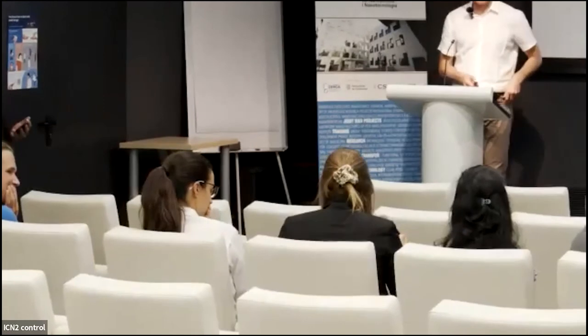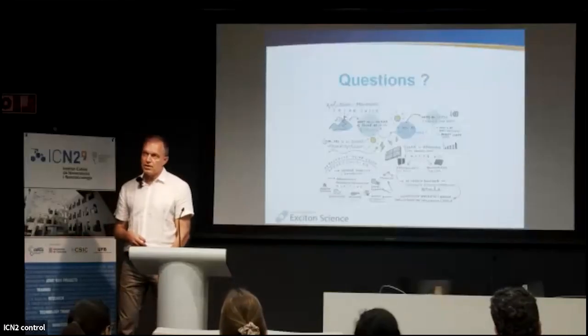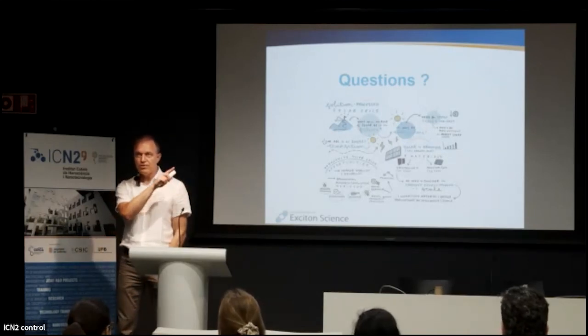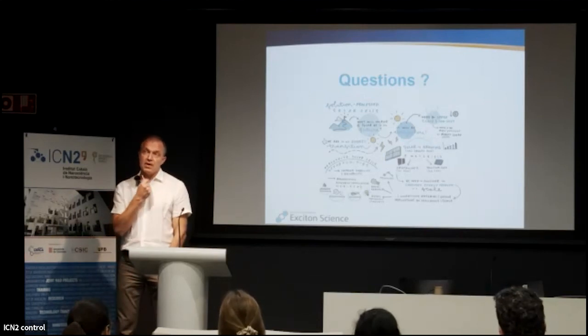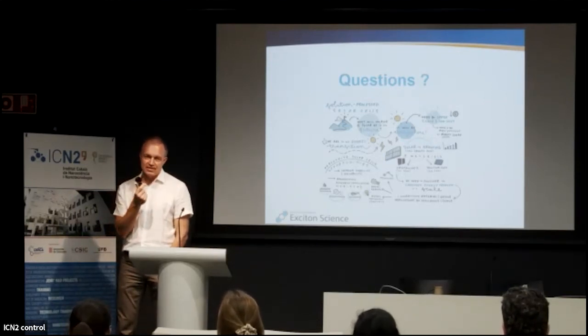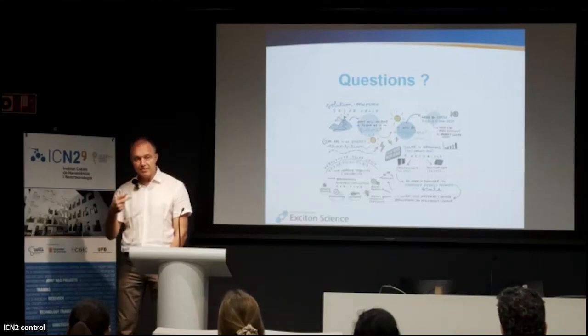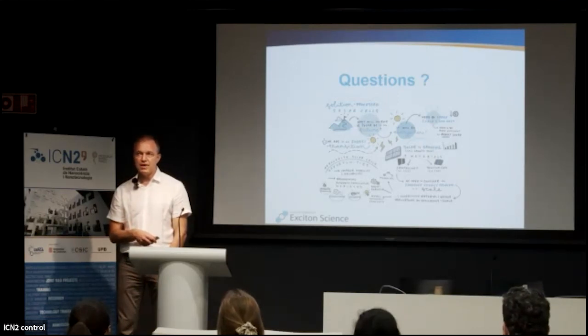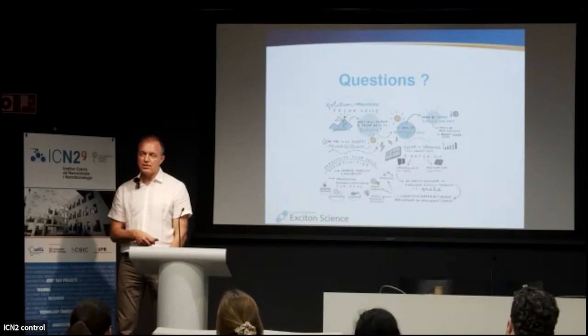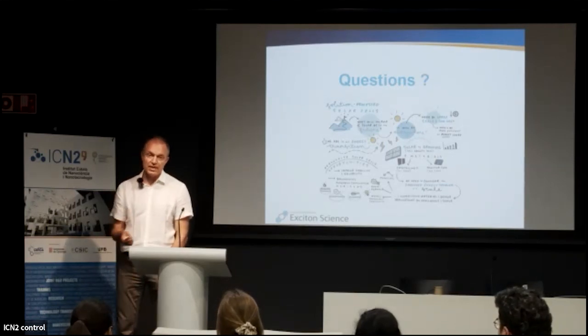I had a question about the timescales for the recovery of the phase segregation. When you saturate it with the high intensity light, is that faster than if you just leave it in the dark with the recovery? I guess it's a diffusion-regulated process. Do you know more or less the difference in the time? From what I showed there, I think within a few seconds we have it. I don't know the exact time scale for the dark remixing. I would say it's at least a factor of a hundred slower. I would say it takes minutes for it to go away completely.